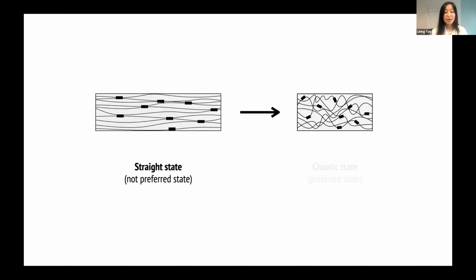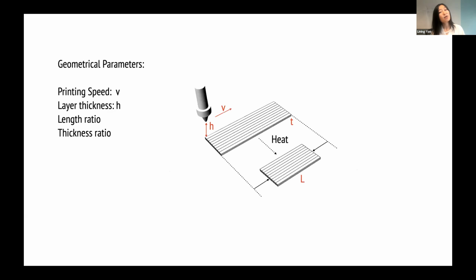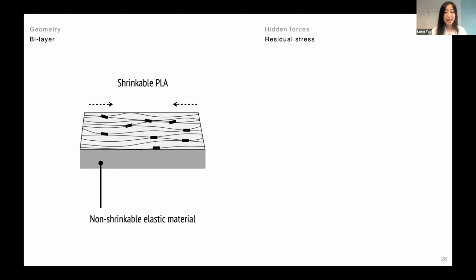So again, this is what I'm talking about. The straight polymer chain after printing shrinks back because that's its most energy-preferred state. That's very simple physics that exists in almost all thermoplastic processing. So there are a lot of geometrical factors that affect how much it shrinks, how fast it shrinks, and also whether or not it shrinks at all. That has to do with each individual layer thickness, but also printing speed, the mixing ratio, thickness ratio, and length ratio. I'm going to talk a little bit about how we control each parameter for different kinds of design purposes.